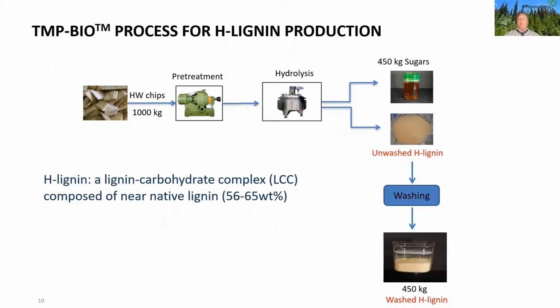On the TMP bioprocess for lignin production, we're using a hydrolysis of cellulose that is done by enzymatic hydrolysis. In the first step, we're starting with hardwood chips. Mechanical pretreatment is followed by a hydrolysis step through the use of enzymes. We're able to produce a very pure and non-toxic, water-based sugar stream and a lignin product that is easily washed with water. The typical product coming out of the process today is a lignin carbohydrate complex, typically composed of 65% near native lignin.